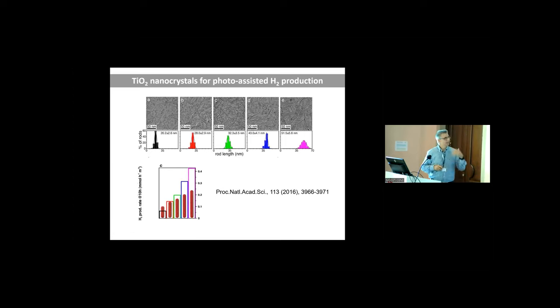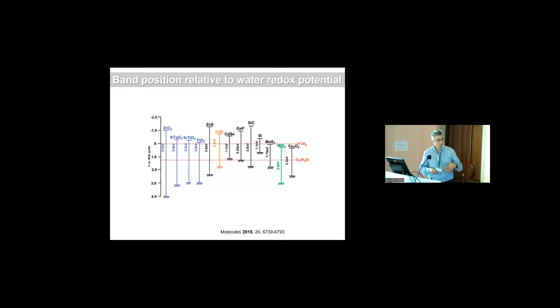It means the anisotropy is playing an important role. And indeed, fast transient absorption spectroscopy proved that by increasing the anisotropy, you increase the lifetime of the photogenerated holes and electrons. Nano is also important because you can transform an inactive material into an active material.